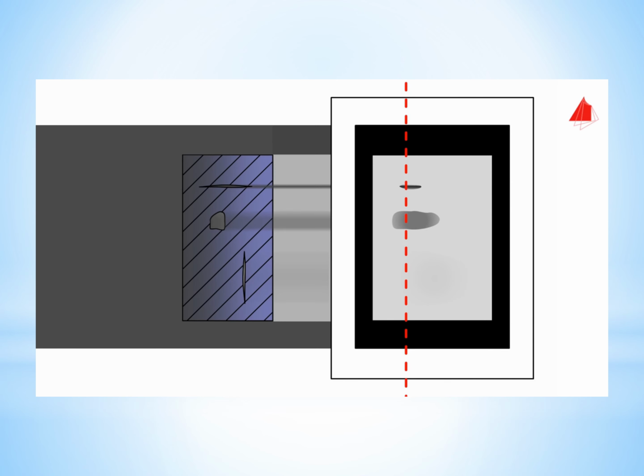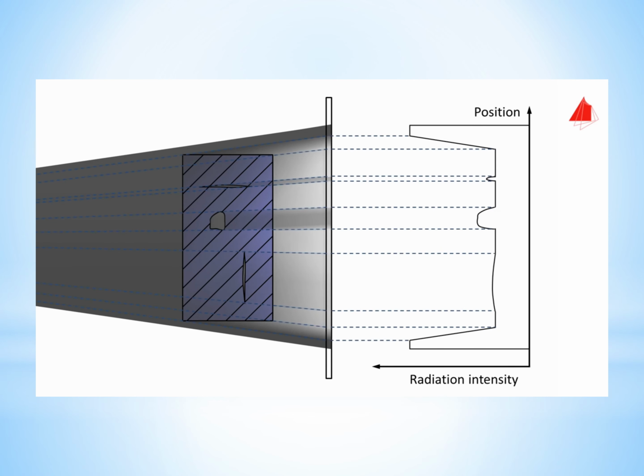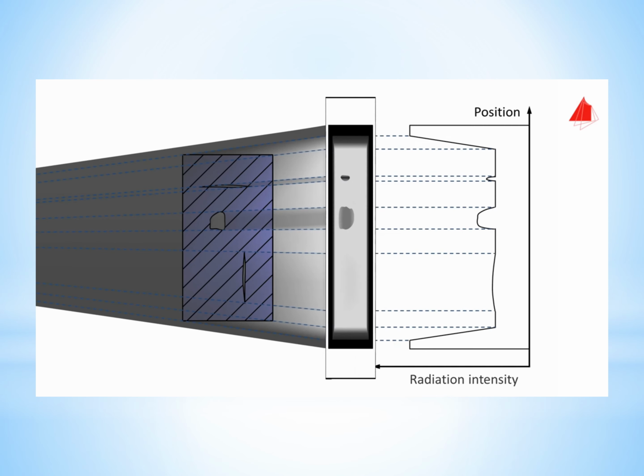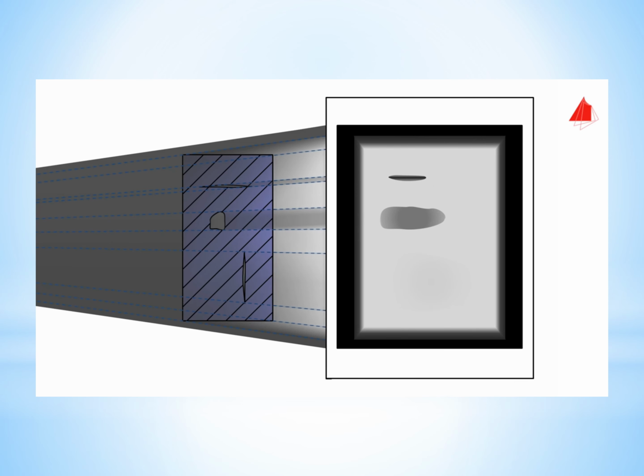And this is what the complete X-ray image of the sample looks like. The originally depicted sectional plane of the sample is shown as a dashed line. Places with defects appear darker because a more intense radiation reaches the image capture unit. As expected, the vertical crack is virtually undetectable. This X-ray image is only obtained with parallel radiation. Using a classical X-ray tube, however, the radiation is cone-shaped. The intensity distribution will therefore look different, and as a consequence, also the X-ray image. The edges of the sample now appear three-dimensionally and not as clearly outlined as before.